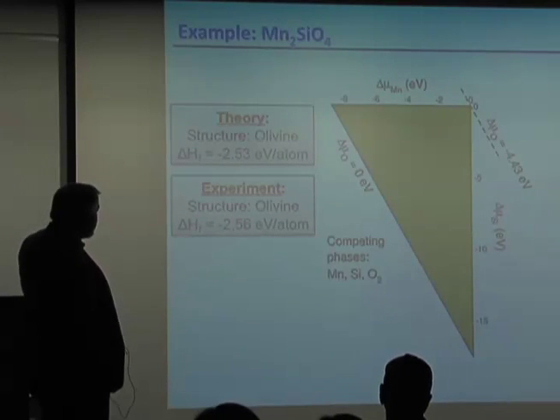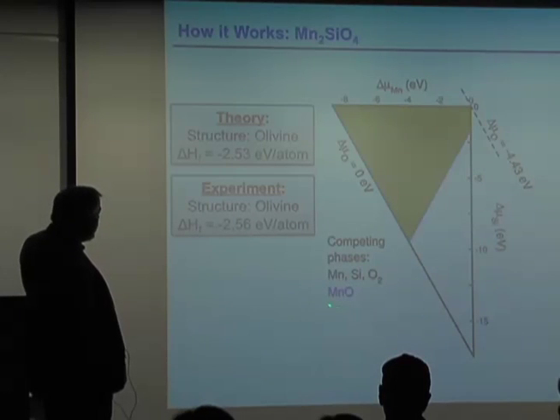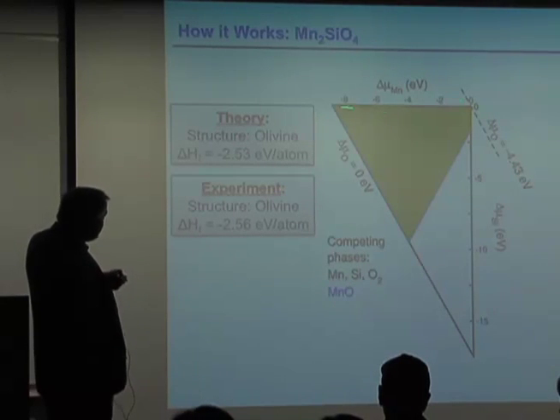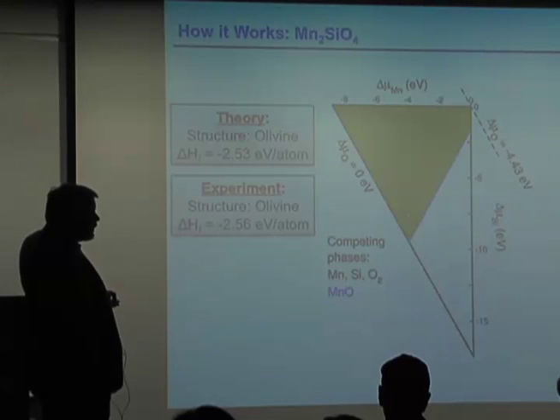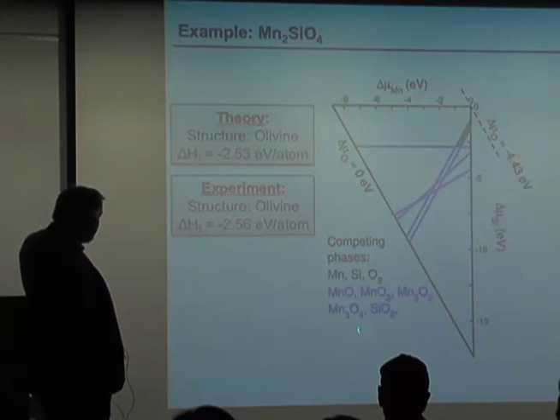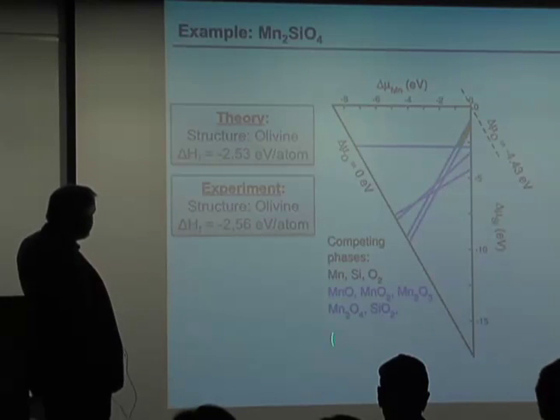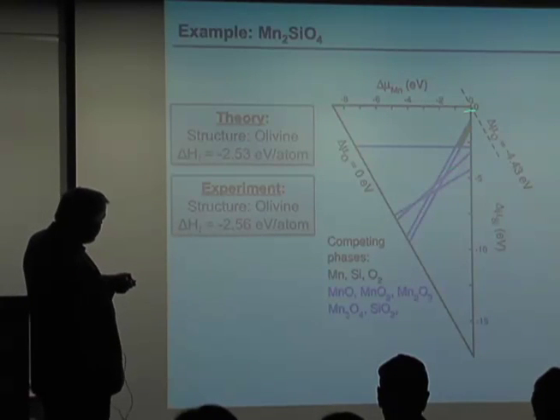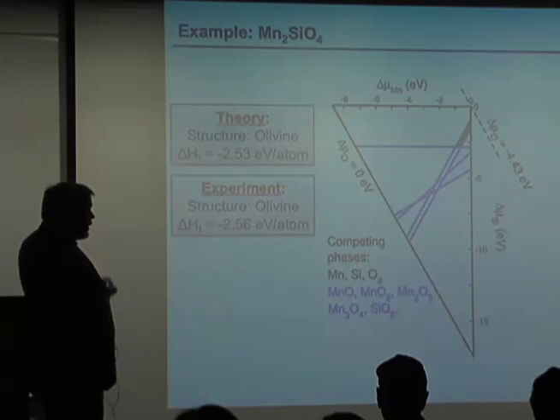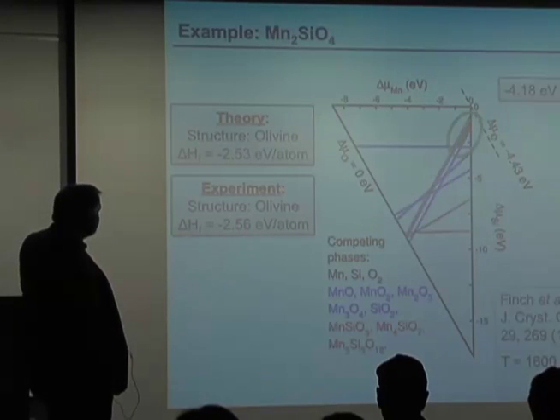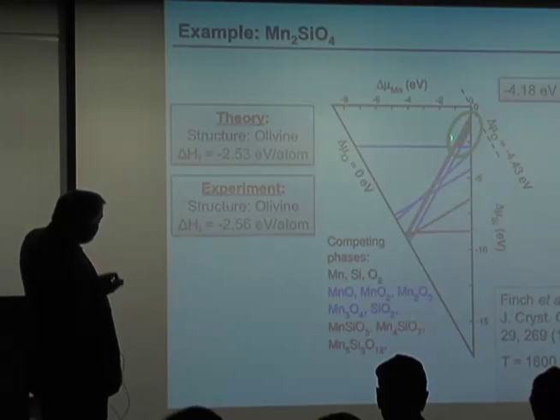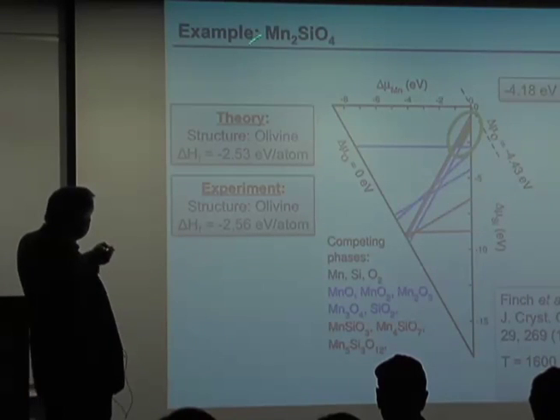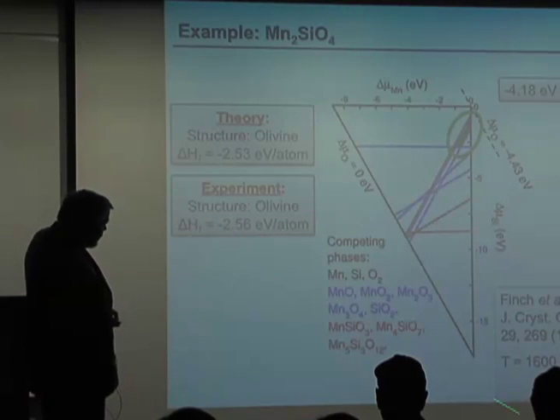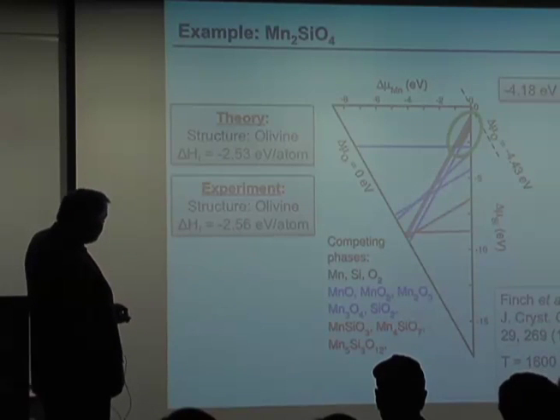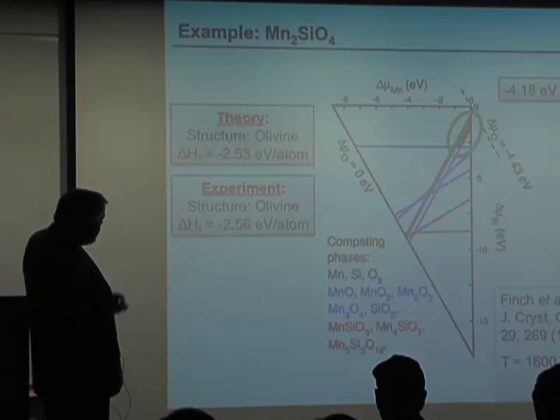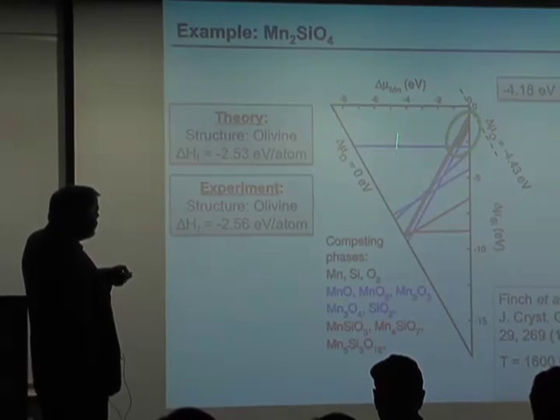But if you start to think about other materials and you bring in MnO as a potential decomposition, you see now it's only stable in a much narrower window than it would be. And if you actually bring in other materials, other manganese oxides, silica, you now find that it actually is only stable within this window. And you can now take these chemical potentials and say, it turns out, if I look in the literature on where this material is actually made, it actually fits right into the chemical potential of oxygen that's right in that window. So you can make it here, you couldn't make it here, you couldn't make it here.